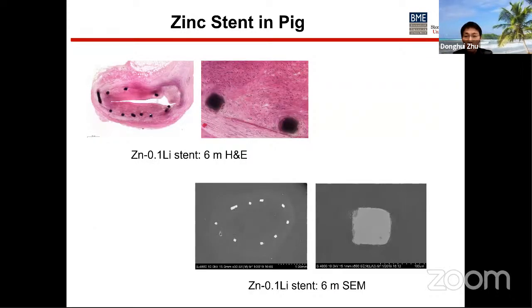Here's some preliminary histological staining. The smooth muscle cell proliferation, however, was a little high. So some neointima was observed, and some surface degradation of the material was revealed by the SEM imaging. Of course, this is pretty much preliminary. More investigation for a longer time period is needed.